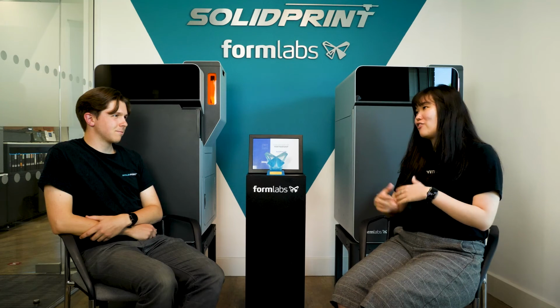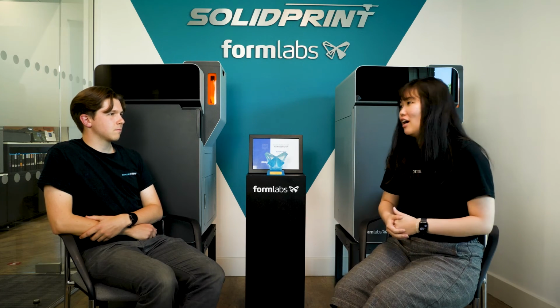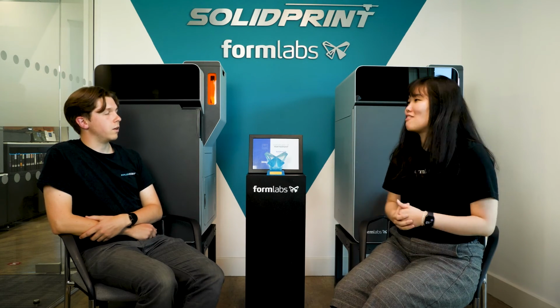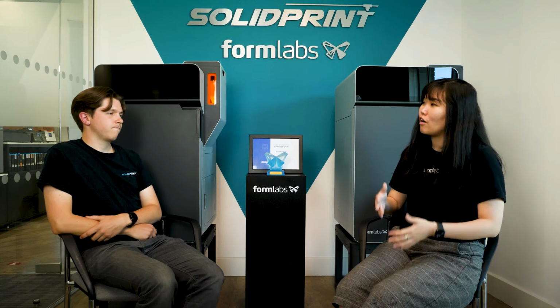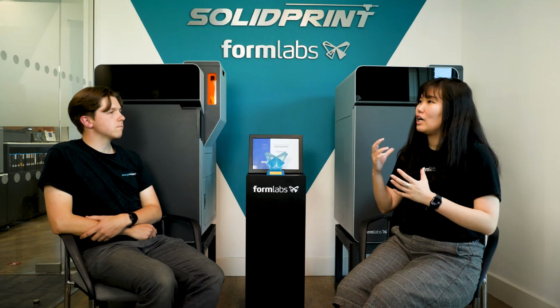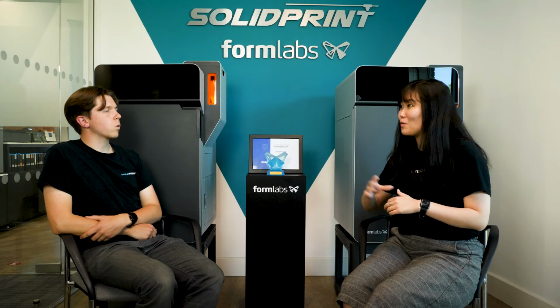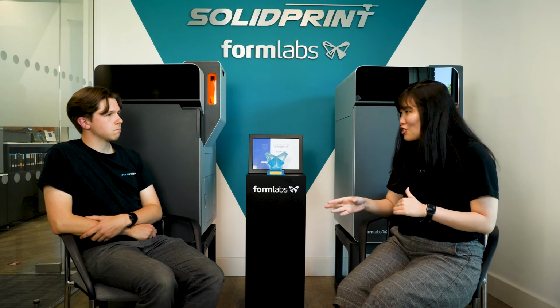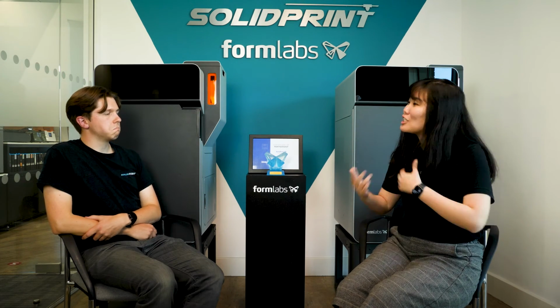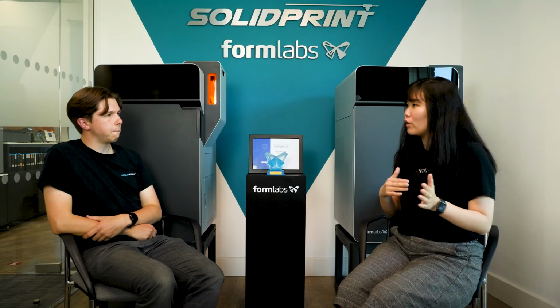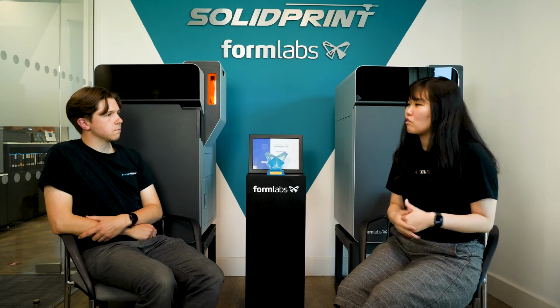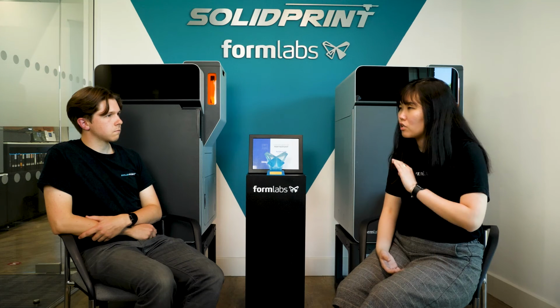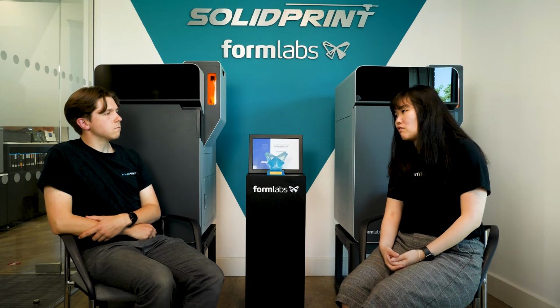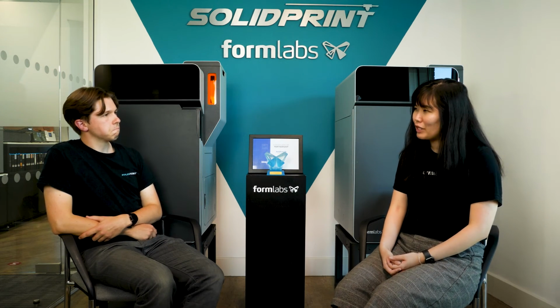Nylon 11 CF, 30% with nitrogen. Without nitrogen, it will be higher. Nylon 11 as well, if you are running it on the Fuse 1+ 30W, it'll be 50% refresh rate without nitrogen. With nitrogen, it will be 30%. So nitrogen does help out with avoiding degradation, so you can lower your refresh rate. So that's a really huge perk with introducing an inert gas atmosphere. But yeah, that's pretty much about refresh rate.